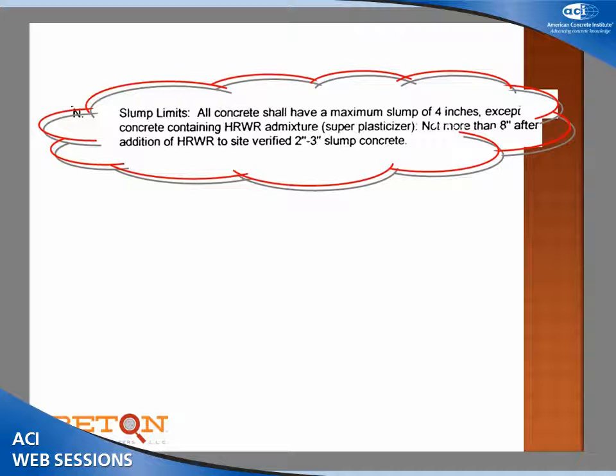Slump limits. This is my favorite one. This is a specification that says the slump limit is going to be 2 to 3 inches before you add whatever the high range is, and no more than 8 inches after. It's pretty reasonable, except the accuracy of batching in a plant versus the accuracy of batching in the field is so different that you don't ever want to be adding admixture to the plant.